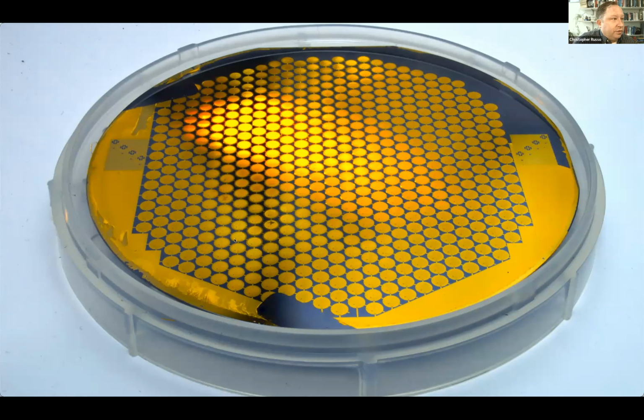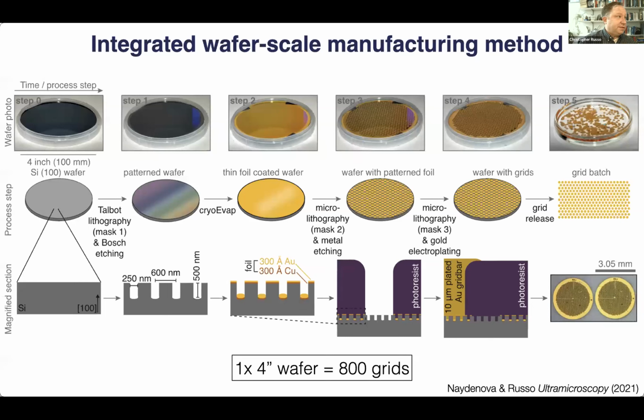And this is one of the first ones we did fully successfully, which we took a picture of. And you can see there's several hundred grids here, close to, not quite, 1,000 on a 4-inch wafer. And you can do this on a 6-inch wafer or an 8-inch wafer, as big as you like. But we did all of this here in the lab. And this is the process. I won't go through it in too much detail, but we just recently published this in Ultramicroscopy.